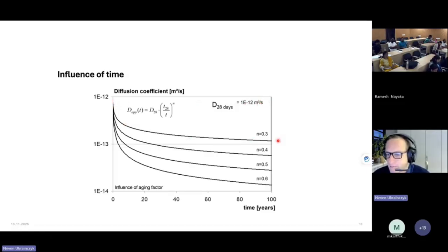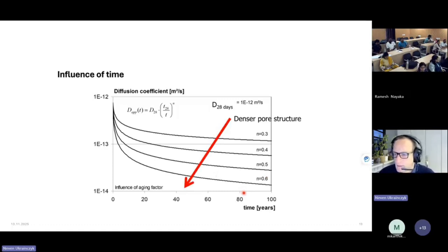And then with time we have different n coefficients, and this n coefficient depends on the binding. This is why I'm telling you it's also binding. Of course, it's also how fast the pore structure refines, so it's also the hydration. But this n depends on your mix design, how much pozzolans, how fast they react, and they have some binding effects, I would also say. So if you have very slow pozzolan, fly ash that's not reactive, it takes a lot of time to react, then this exponent increases. That's how it's explained, because the pore structure gets more dense because of the late pozzolanic reactions.